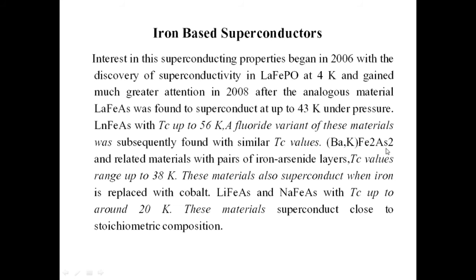Barium potassium Fe2As2 and related materials with a pair of iron arsenide layers have critical temperature values ranging up to 38 Kelvin. These materials also superconduct when iron is replaced with cobalt. Lithium iron arsenide and sodium iron arsenide have critical temperatures up to around 20 Kelvin. These materials superconduct close to stoichiometric composition. This is all about the iron-based superconductors.